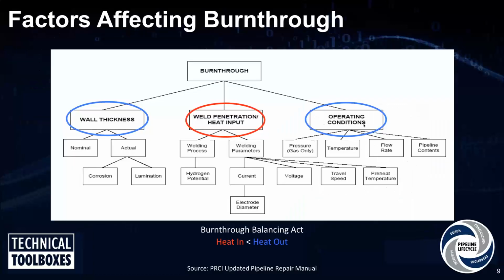So these are all the factors that are commonly attributed to burn through risk, right? There are a lot of sub factors here, but the three primary ones are really the wall thickness of the pipeline, how the weld is made, and the operating conditions of the pipeline itself. And really, when it comes down to burn through, it's a balancing act. And the balancing act is about how much heat goes in versus how much heat leaves.